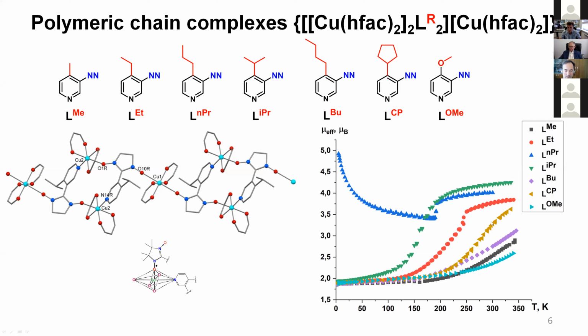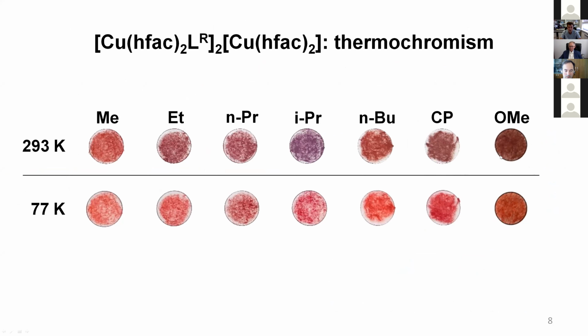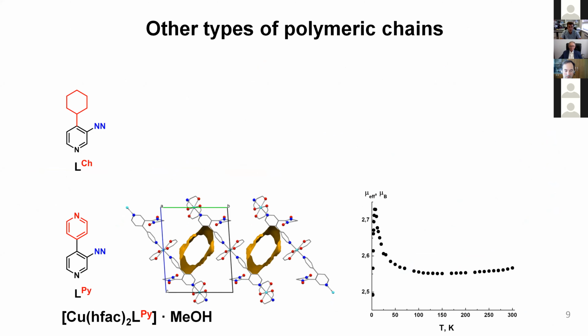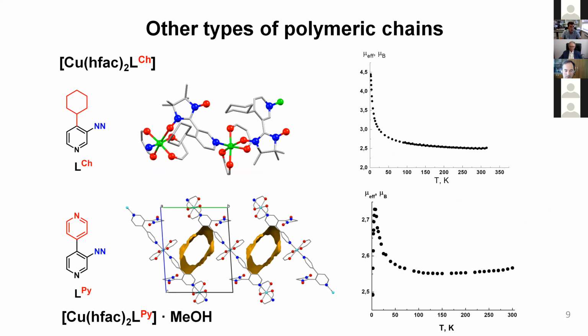The transitions for other complexes look unfinished at room temperature, and the maximum cannot be reached because of thermal instability above 360 Kelvin. For all complexes, a thermochromic effect is observed. In the case of cyclohexyl and pyridyl-substituted nitronyl nitroxide, there are no cyclic fragments, and the chains are built due to the coordination of the ligand with copper through the nitrogen atom of the pyridyl ring and the oxygen atom of the nitroxide group, or through the nitrogen atoms of pyridine rings.